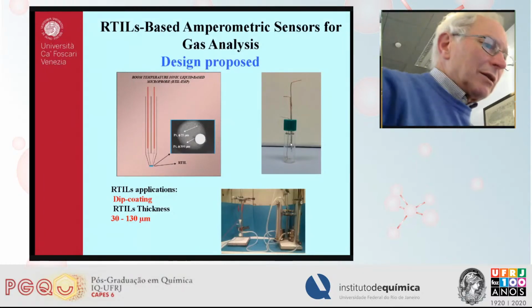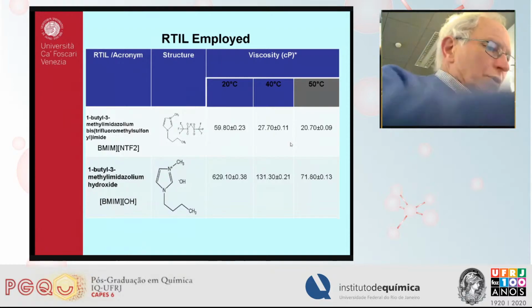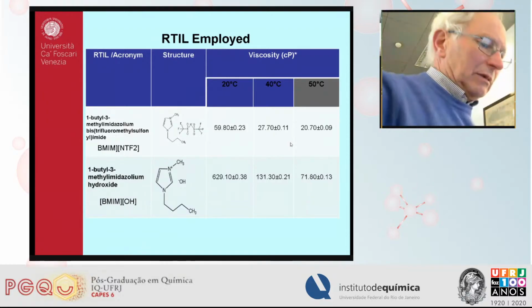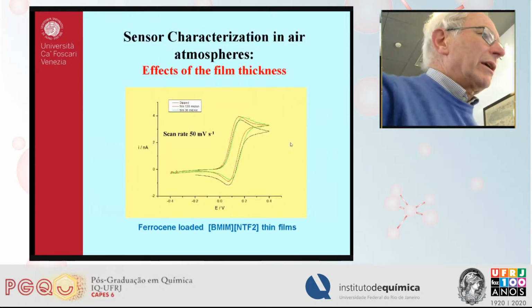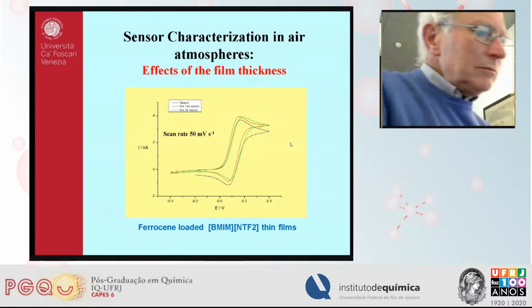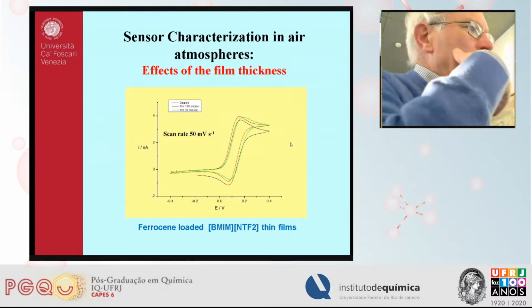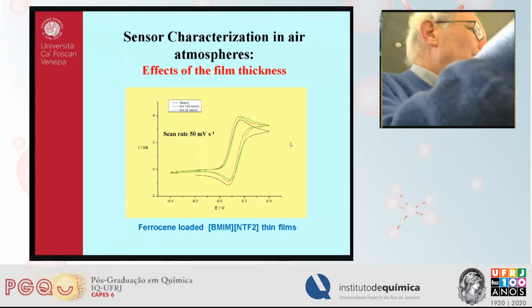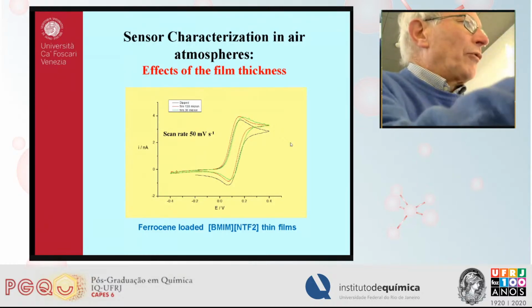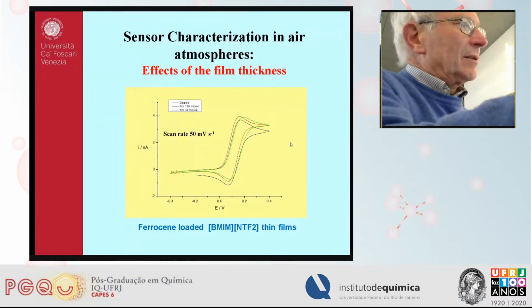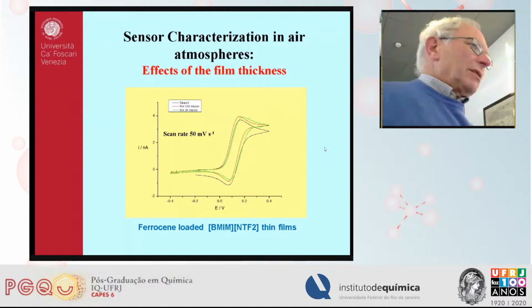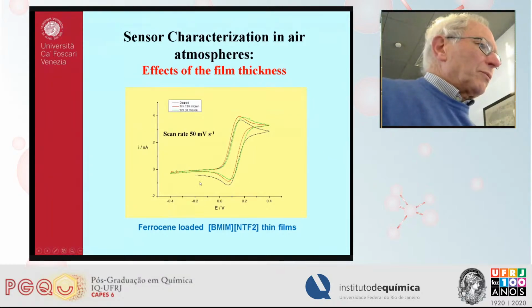So we tested this system using different ionic liquids. Here there are some characteristics of the ionic liquids. And also, before starting with measurement in the gas phase, we want to verify which kind of responses we obtain in this media. So this is, for instance, the response we obtained by room temperature ionic liquid, this one in particular, which was loaded before with ferrocene.